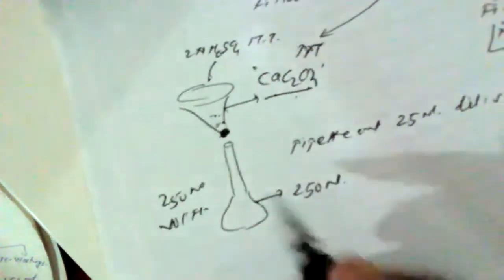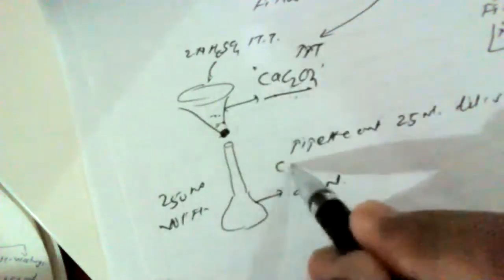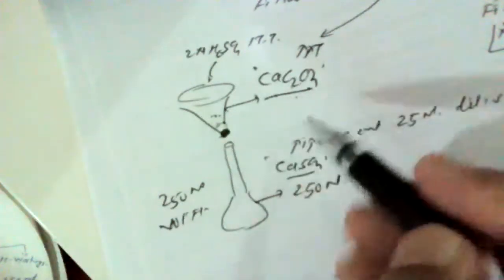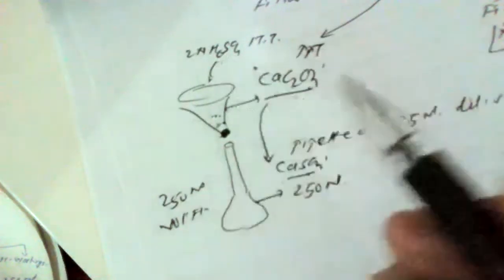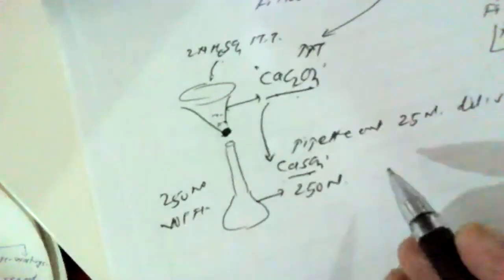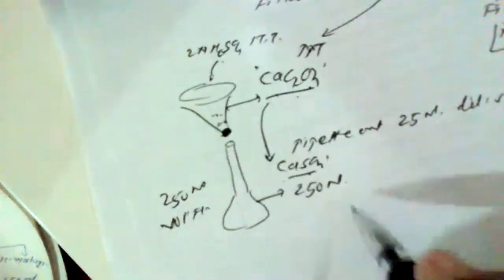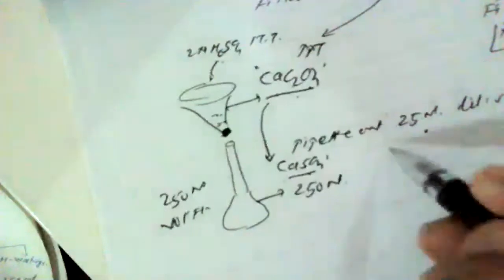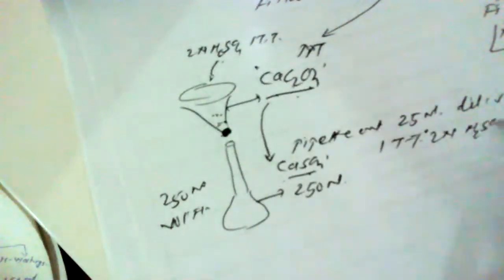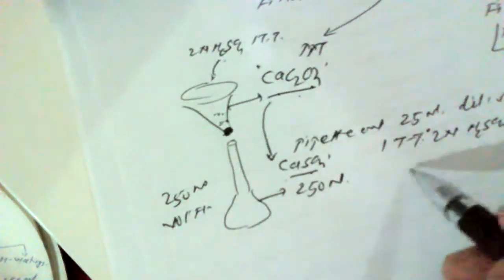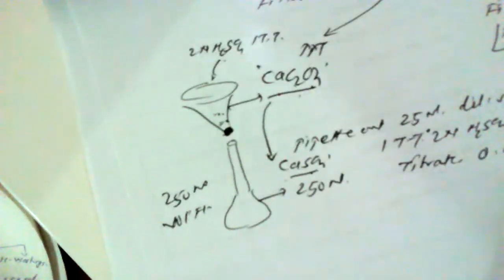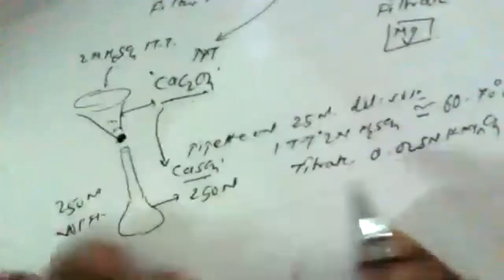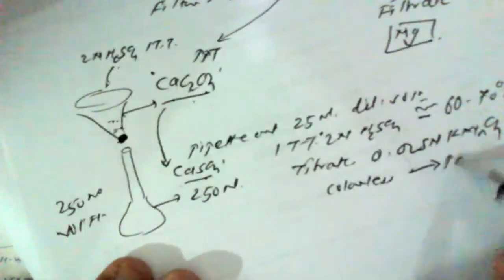After dilution, we have to pipette out 25 ml of this diluted solution of calcium oxalate. So here, after adding sulfuric acid, calcium oxalate will be converted into calcium sulfate. So calcium oxalate is converted into calcium sulfate by adding sulfuric acid, so it gets dissolved. Now, to this 25 ml of the solution that is pipetted out, we have to add 1 test tube of 2 normal sulfuric acid. This solution is to be heated to approximately 60 to 70 degrees centigrade, and all these contents are to be titrated against 0.025 normal solution of potassium permanganate. Here, the end point is colorless to faint pink color.